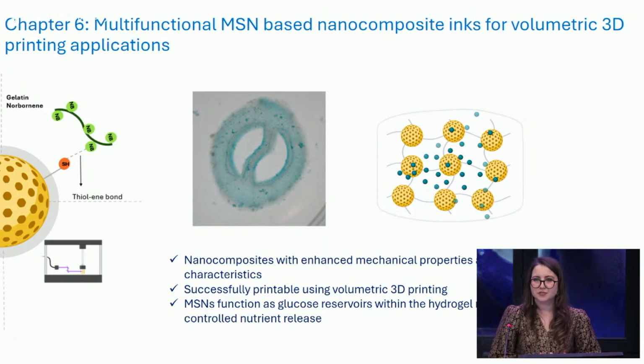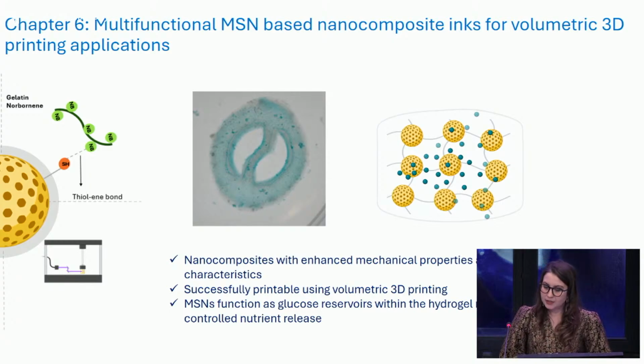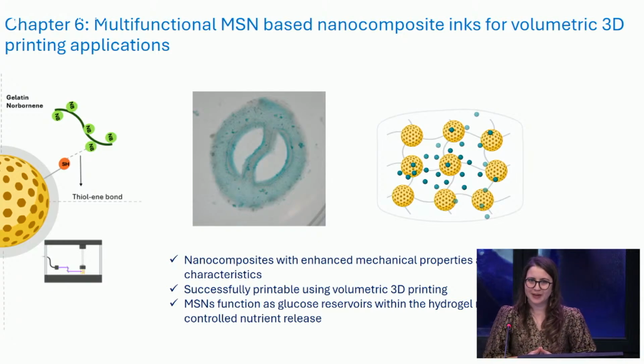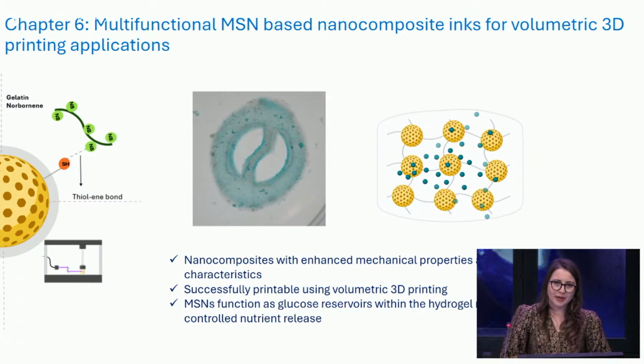In chapter 6, we shifted our focus to volumetric printing, which is a state-of-the-art technology that allows fast fabrication of millimeter-scale constructs with complex geometries in a few seconds. For this chapter, I developed nanocomposite inks by combining thiol-functionalized MSNs with norbornene-functionalized gelatin. Here, gelatin is a well-established natural polymer in volumetric 3D printing. However, like many traditional single-network hydrogels, gelatin-based inks suffer from weak mechanical properties as well.